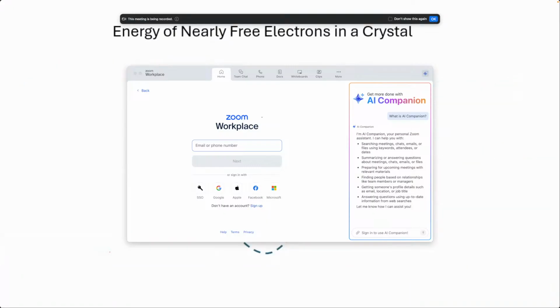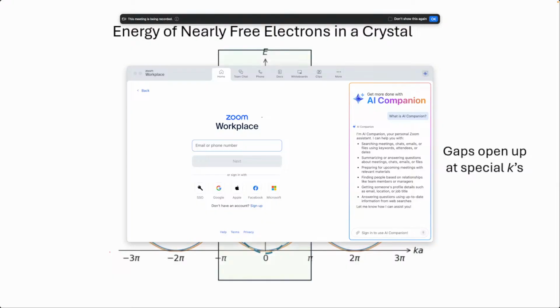Wonderful. The energy of a nearly free electron gas had a parabolic form like k squared by 2m. Now, once you have a crystal potential, these energies get modified, and you will see a gap opening up at some special points, and these points are called zone boundary points, the boundaries of the Brillouin zone, which defines a periodic unit in the reciprocal space. So these types of gaps open up, but elsewhere you will see the energies are more or less very similar to the free electron picture. So gaps open up at special points.